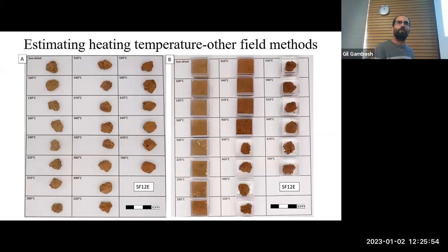You can see the change from about 400 degrees. This is actually what archaeologists usually do. They see these red, hard bricks and say that they were burnt, but actually these were also burnt. They're not red and they're not hot and they're not hard, but they were also burned, just to lower temperatures. So this is a good tool in the field. Of course, the color can change from other factors as well, like oxygen and so on. So it's not a perfect tool, but it's useful, especially in the field.